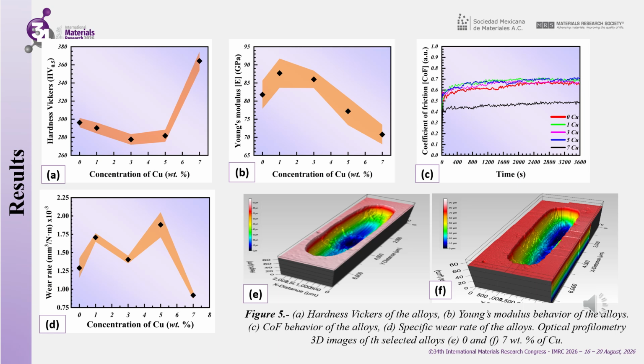This pronounced increase at a higher copper concentration indicates significant hardening of the material. This behavior has been shown to be associated with microstructural modifications induced by the incorporation of copper, such as changes in the distribution of alpha plus beta titanium phases, microstructural refinement, and solid solution hardening. Consequently, the findings suggest that the impact of copper on hardness does not strictly follow a proportional relationship with its concentration. Instead, there is a composition-dependent response, with the effect being particularly pronounced at 7% copper.